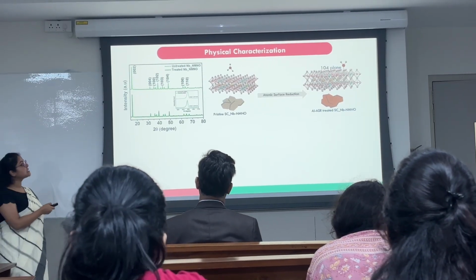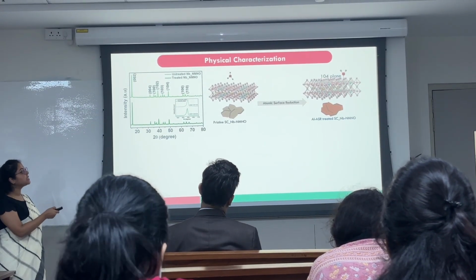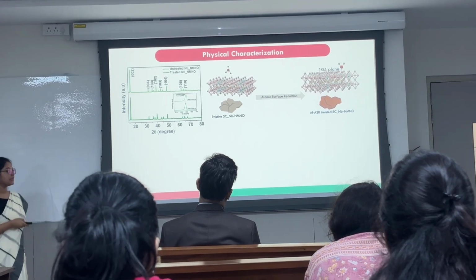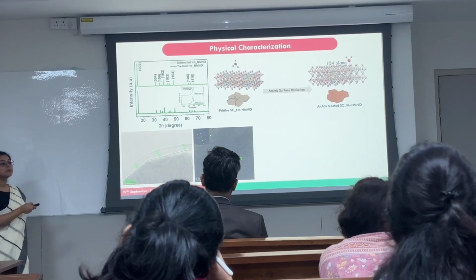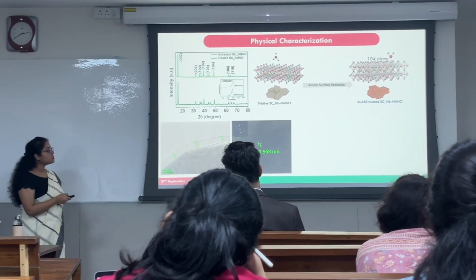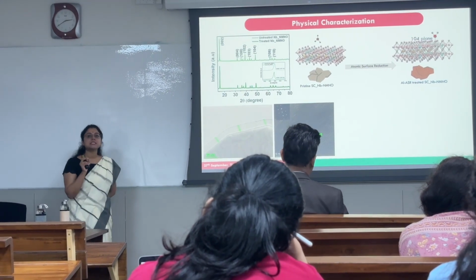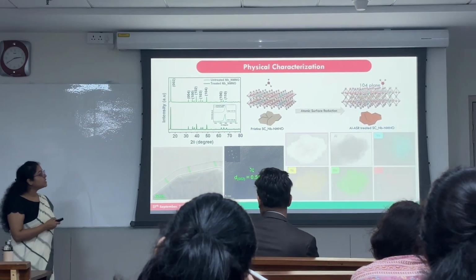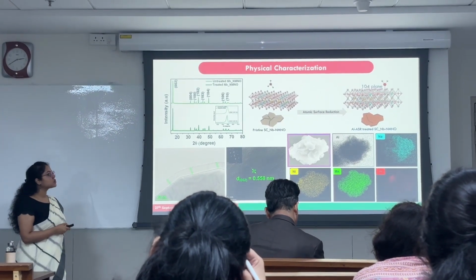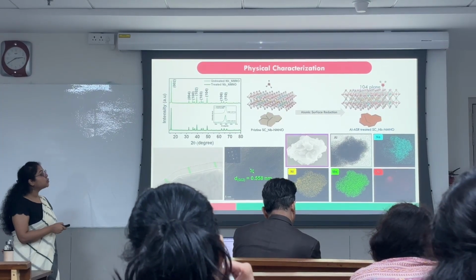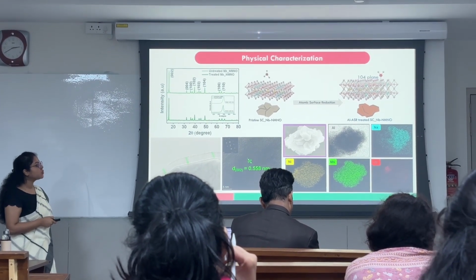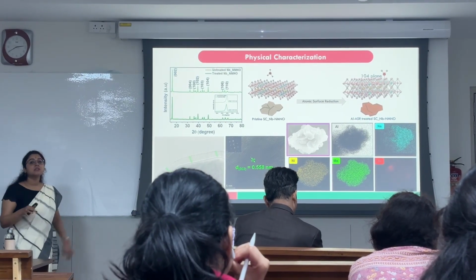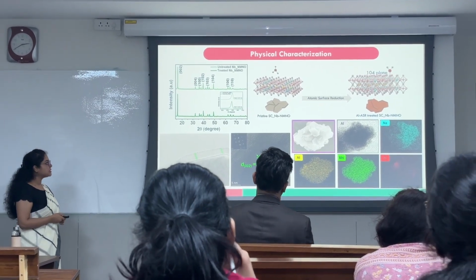And through the DFT analysis, we observe that the trimethyl aluminum gets attached at the 104 plane. Through the FE-TEM analysis, we observed that we were successful in obtaining a uniform coating, and through the high resolution TEM, we observed that there hasn't been any change in the bulk, because the d-spacing of the 002 plane remains the same as that of the pristine cathode material. Through the SEM and EDS analysis of the secondary particle, we observed that aluminium is only on the surface, whereas sodium, nickel, manganese, and niobium are homogeneously distributed throughout the crystal.